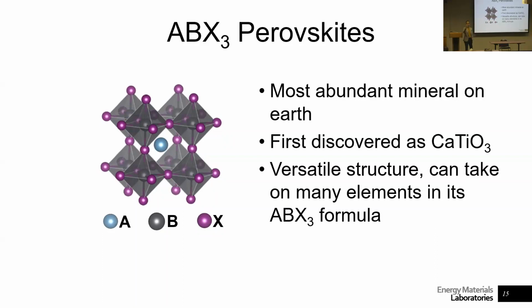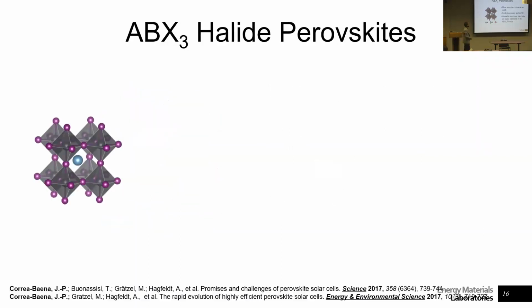So we can exchange some of these elements for other elements. In the case of oxygen, we can exchange it for halide, iodine, bromine, or chlorine. In the case of this cation, calcium, which normally has a charged state that sits right in the middle there, we can have an organic material, or we can have an inorganic, but it has to be normally a 1+ state. And then the metal here in the middle can also be swapped by many other alternatives.